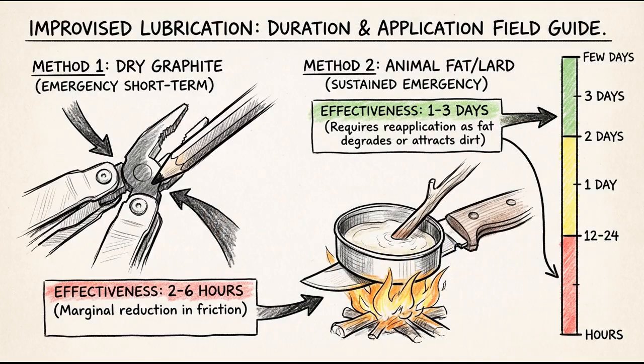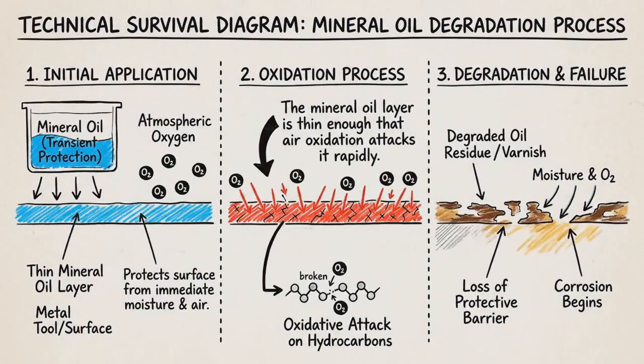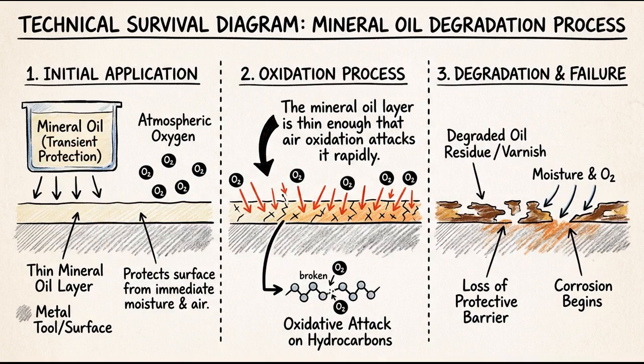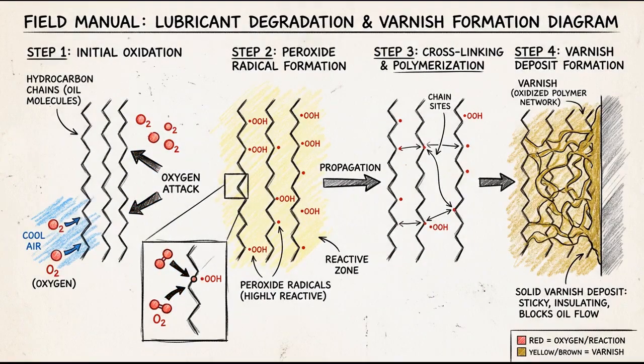The mineral oil layer is thin enough that air oxidation attacks it rapidly. Oxygen molecules react with the hydrocarbon chains, creating peroxide radicals that cross-link the oil molecules into a varnish. This varnish is sticky, not slippery. It increases friction rather than reducing it.